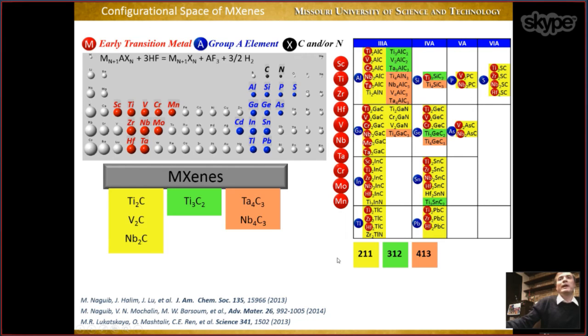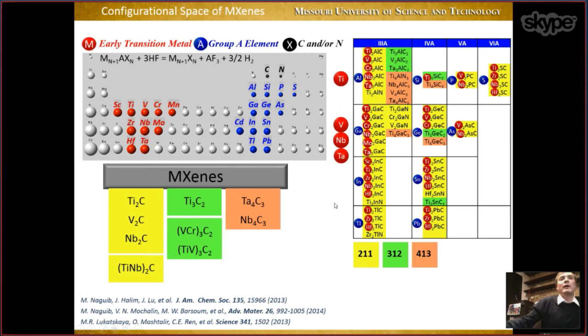Okay. Now, what we have produced so far is not that much. We actually produced MXenes only with these elements as M elements. And we produced mixed MXenes where we have solid solutions in M sites. So it can be titanium niobium carbide, for example, titanium vanadium or vanadium chromium carbide.